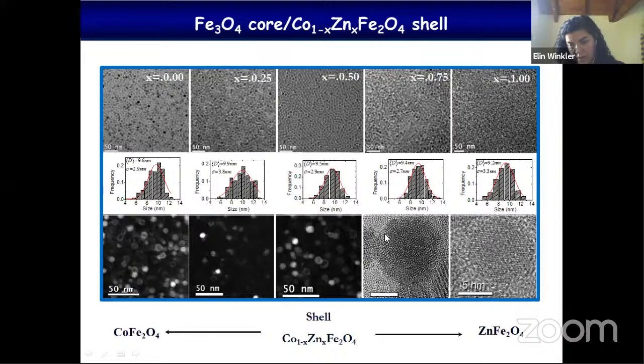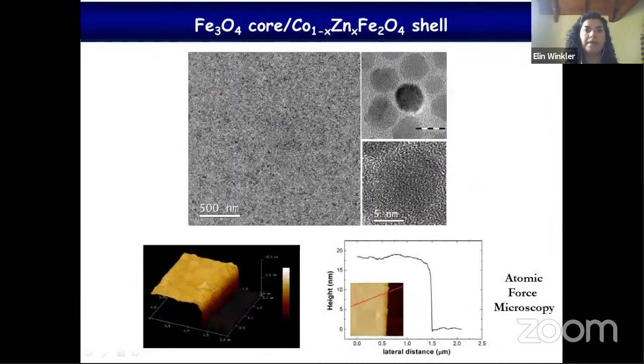In this case, for example, you can observe the crystalline planes of the shell. And this one is a dark field image. In this case, I want to show that in this way you can grow a very uniform layer of several microns. This is more than 1 micron, and you can see all the nanoparticles. And you can observe that between the nanoparticles there is a small gap that corresponds to amorphous carbon that remains from the synthesis.